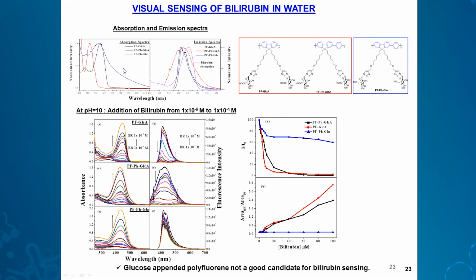So here again, the emission of these polymers matches the absorption of bilirubin. So these could be used here. Left side is the absorption spectrum of these three polymers with increasing addition of bilirubin, and right side is the quenching of the fluorescence. The first two are the glucuronic acid based polymers, and the last one is the reference glucose based polymer. Immediately you can see that the glucose based polymer is not so sensitive, not so useful.